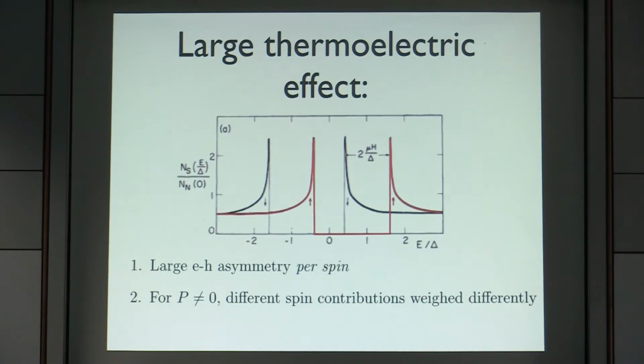Let's look at this spin-split density of states a bit closer. What we see is that the superconductor actually still knows where the zero is, because that's basically the chemical potential of the superconductor. For example, the spin up density of states has a very large electron-hole asymmetry, because the holes have a density of states much closer to zero than the electrons. The spin down is of course exactly the opposite, so that the spin-averaged density of states is still electron-hole symmetric. But if you have a contact with the ferromagnet, you should not weigh them with the same weight. This combination of these two effects leads to very strong thermoelectric effects.